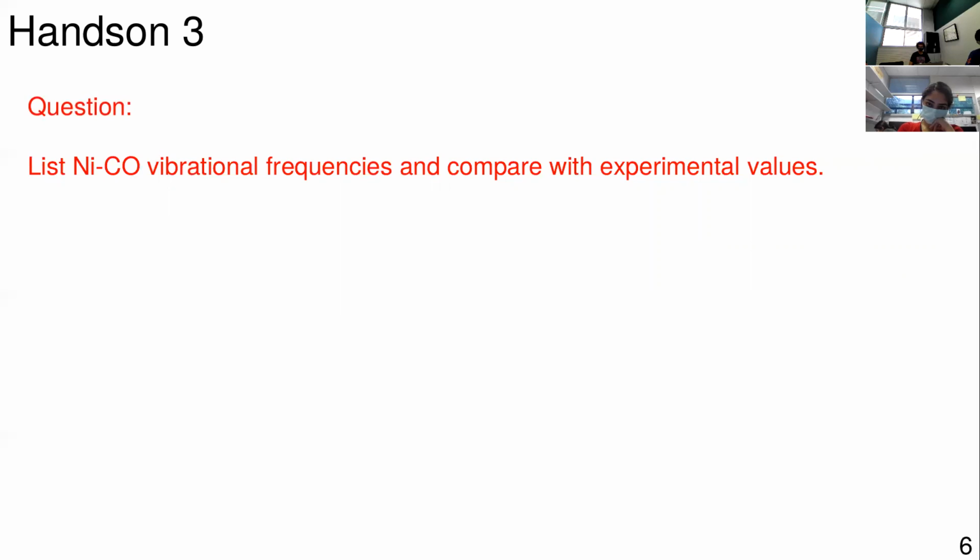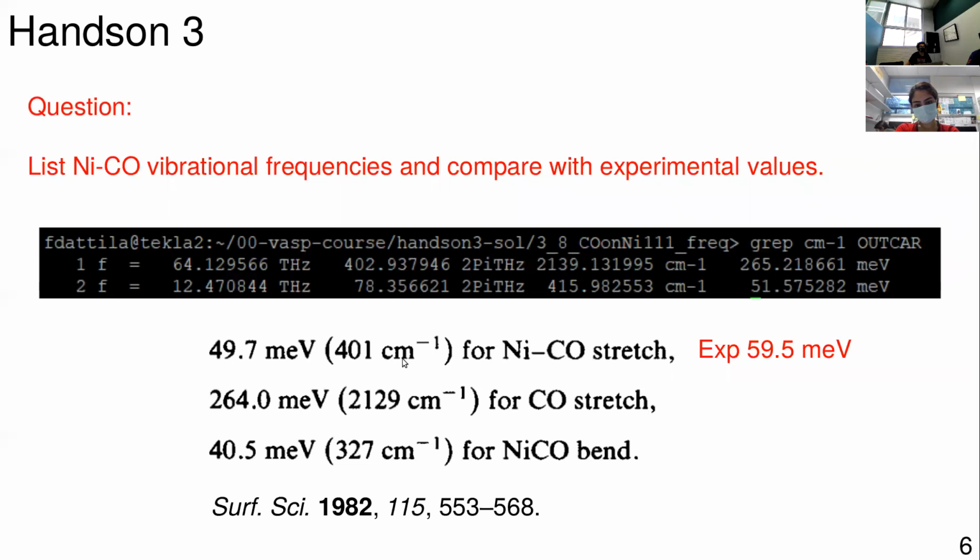Yes. Okay, how much? The frequency between the carbon and the oxygen was 2139, and the surface with the carbon it's 415. Okay, yeah. So these are the two values that Henrik just said, exactly. And as for the experimental value, I found this paper that is actually a DFT paper. So these values are DFT calculated, and the only experimental value is this one.